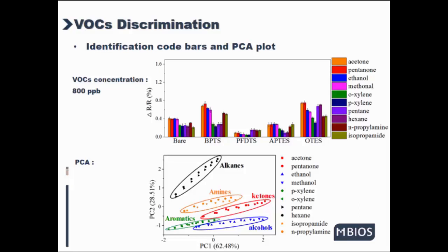And the signals obtained from the sensor response were also analyzed with PCA after the signals were normalized to their initial values. A clear classification of 5 clusters related to different kinds of VOCs can be observed, enhancing the ability of the nanowire gas sensor Inno system fabricated by the NAMIC approach to recognize and separate different VOCs.